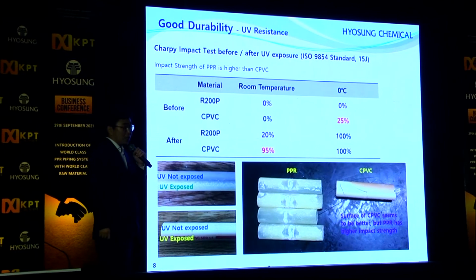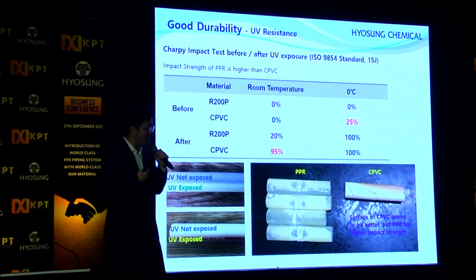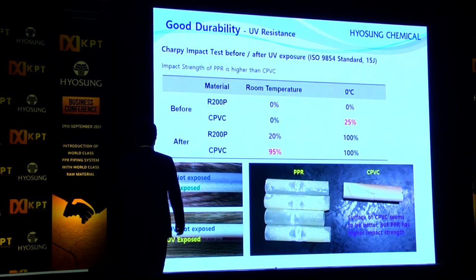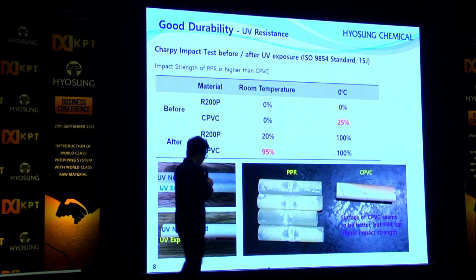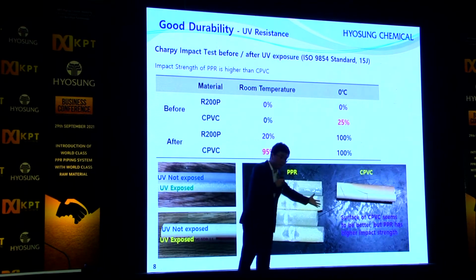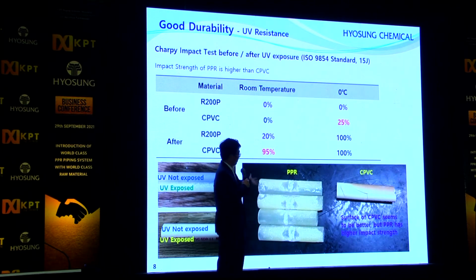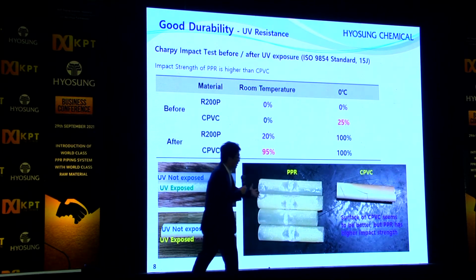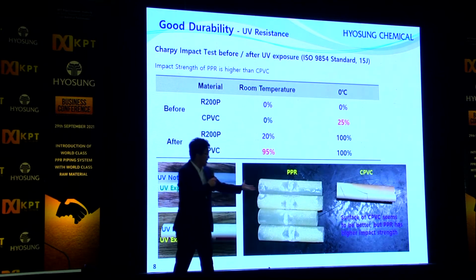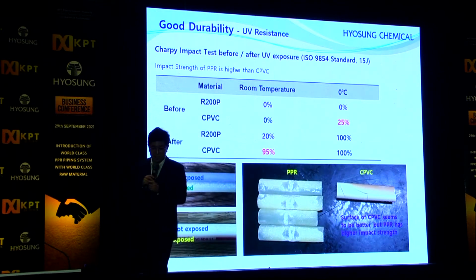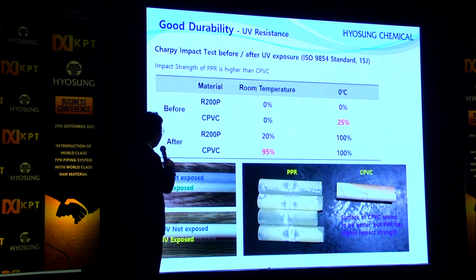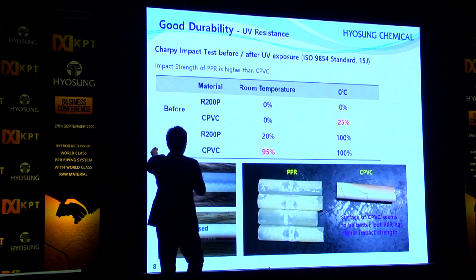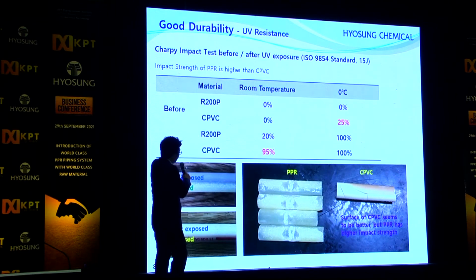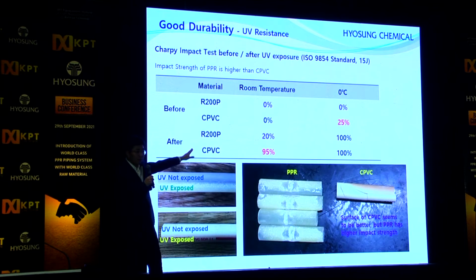This is a UV resistance test we conducted ourselves in our lab. You can see the pictures after UV exposure. The surface is very dirty, but CPVC seems to be very nice. But let's see the results. Before exposure, at room temperature, 0% breakage. But after UV exposure, R200P only 20% broken. But CPVC, 95% broken.